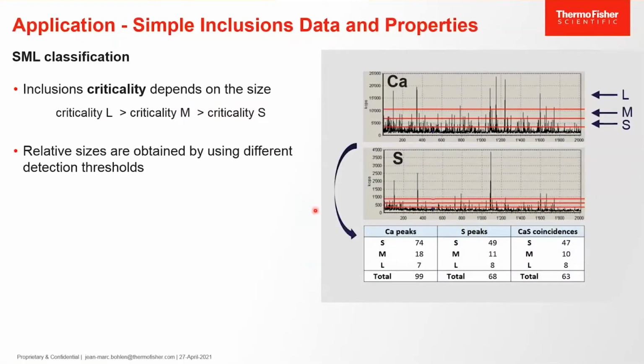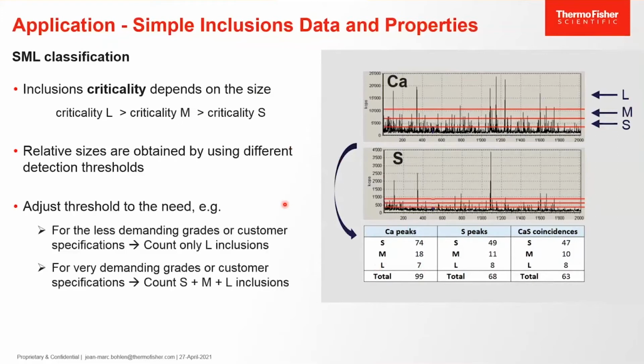The relative sizes, S, M, L, are obtained by using different detection thresholds, as you can see on this calcium run chart. One threshold to detect the small, one to detect the medium and one to detect the large inclusions. You can do that on all the elements, and at the end you obtain the counts for the different categories of inclusion.